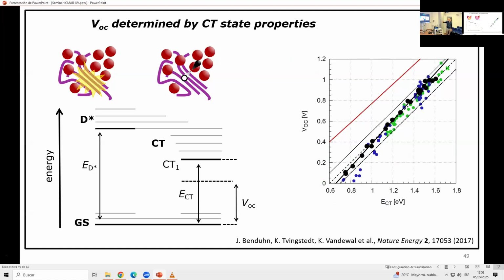The other thing is that, because of that, this state has an energy gap, and it's that energy gap which will then determine the electrical properties, the voltage of your solar cell. So you see here that CT state energy plotted for 100 or 150 different donor acceptor combinations. And you see, if the CT state energy goes up, this interfacial energy goes up, your open circuit voltage goes up. So an easy design rule is: make sure the CT state energy is as high as possible. And then the question is, how high can you make it? Can you make it as high as the neat material gaps or not?